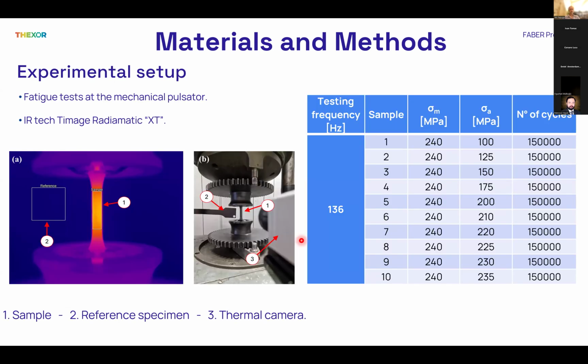The experimental setup is reported in this slide. This picture reports the mechanical pulsator adopted for the fatigue test. Regarding the thermal emissions acquisition, in order to estimate the fatigue limit using the thermographic method, the thermal camera was placed in front of the surface of the sample during the fatigue test. The table on the right side reports the stress amplitudes adopted during the thermographic approach and the corresponding number of fatigue cycles adopted during the thermal emissions acquisition.